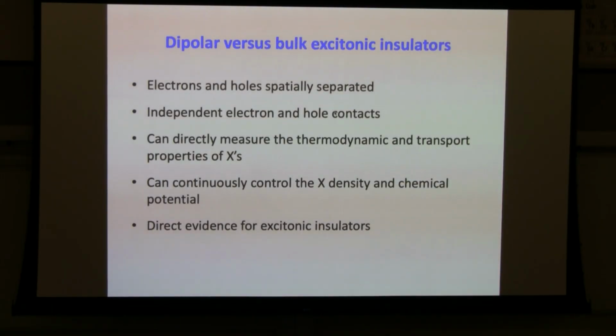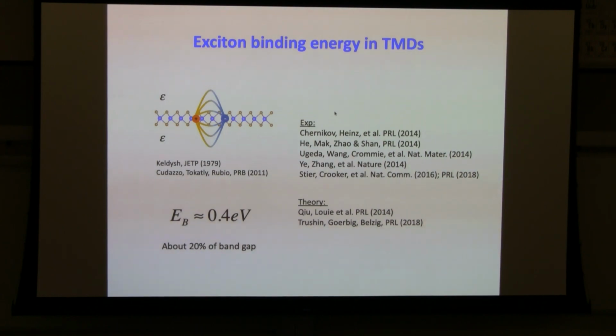Okay, so compared to the bulk excitonic insulator I mentioned, the electrons and holes are now separated in real space, into two layers. So you can easily make electron and hole contacts to each individual layer. And you can also directly control the exciton density and exciton chemical potential, as well as measure the thermodynamic and transport properties of the excitons that I'm going to show you. And as a result, you can provide direct evidence for the excitonic insulator in this system, which I try to convince you.